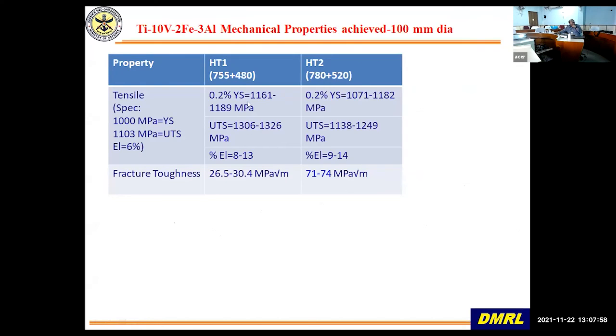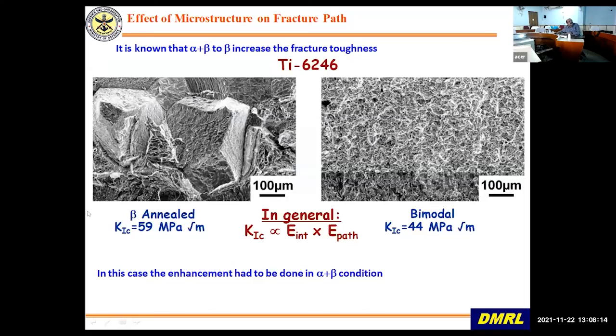And here I'm just showing you the first heat treatment that we did. We wanted high strength, we got it, but we got very low fracture toughness. So we modified the heat treatment, higher solution treatment and higher aging temperature, and we could increase the fracture toughness, although we compromised on strength, which is okay. And it is very easy, as I told you, to improve fracture toughness in a beta treated material, but in a bimodal material, it is not very easy to increase the fracture toughness.